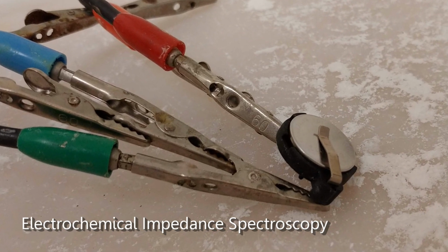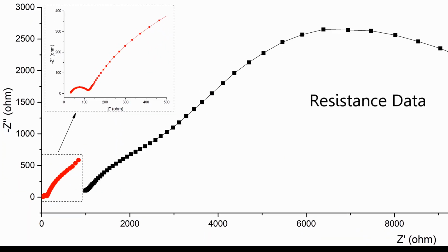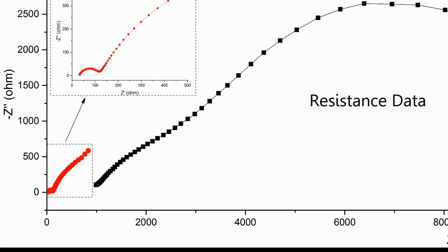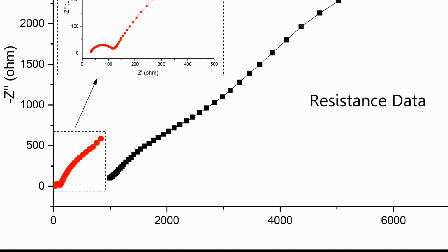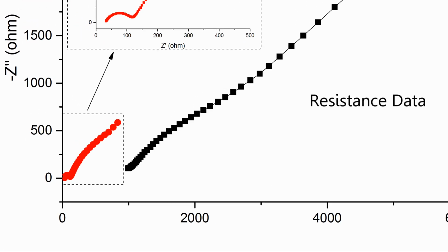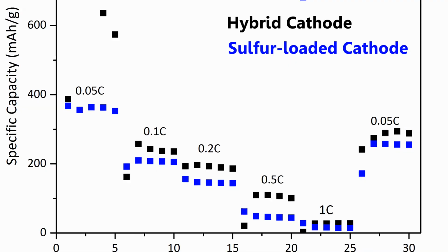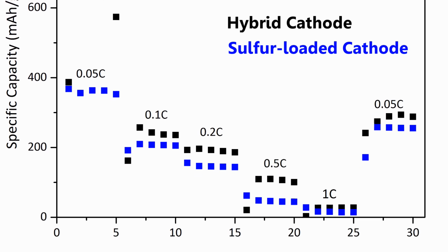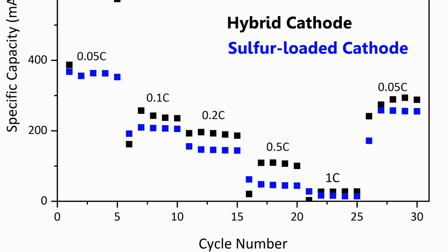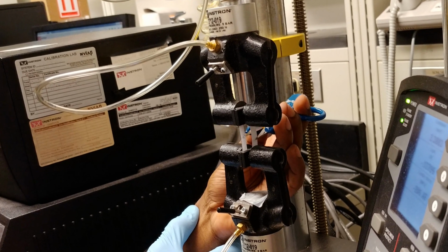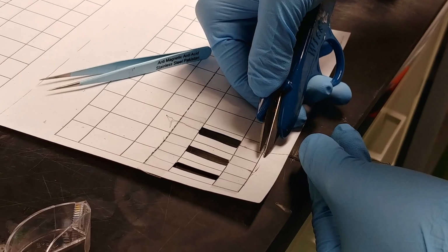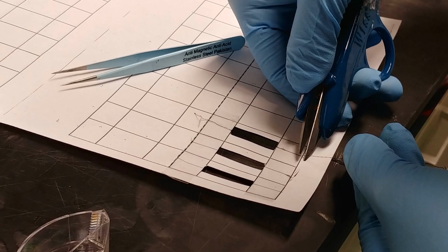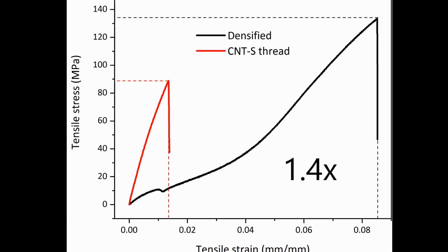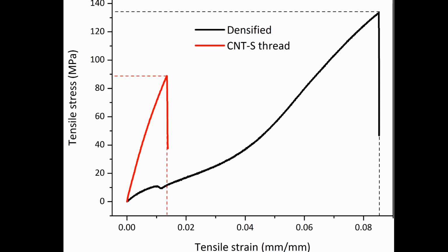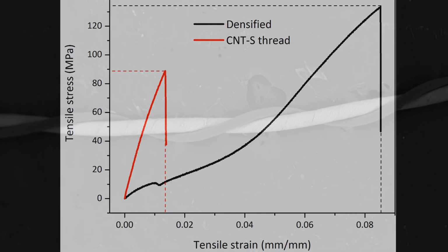When compared to the original sulfur-loaded cathode, the resistance of our hybrid cathode was approximately 30 times smaller, making the hybrid cathode 30 times more conductive. A battery analyzer showed that our hybrid cathode also had capacity improvements at different discharge rates. We used a tensile tester to look at the tensile strength of each part of the hybrid cathode. We found the densified thread had a 1.4 times higher tensile strength than the original sulfur-loaded thread.